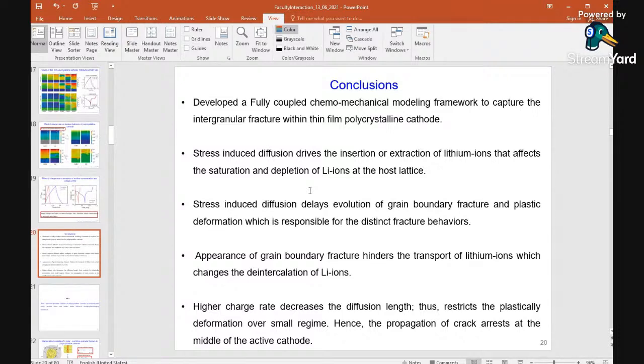We saw that the stress-induced diffusion delays the evolution of grain boundary fracture. Appearance of the grain boundary fracture hinders the transport of the lithium ion and changes the deintercalation of the lithium ion. Obviously, we have studied one cycle, so it can go for multiple cycles. We can see higher charge rate decreases the diffusion length and restricts the plastic deformation over a small zone, and that's the way the propagation is arrested in the middle. So I'll go for the next.